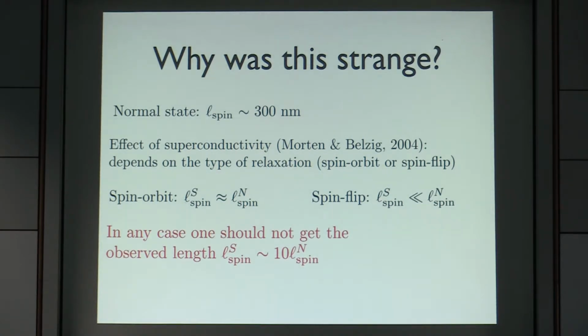So qualitatively, can you explain why in superconductivity the spin flip length is much longer than in a normal state? It's because you're screening the magnetic impurity? No, I mean it should be much shorter. Okay, it should be much shorter in the superconducting case, but the observation was that it was 10 times longer. And this was the mystery that I'm trying to explain now during the talk.